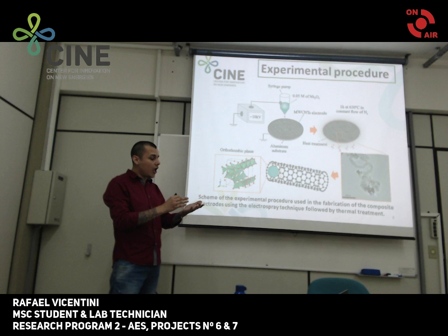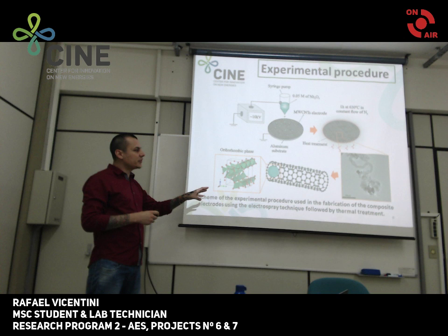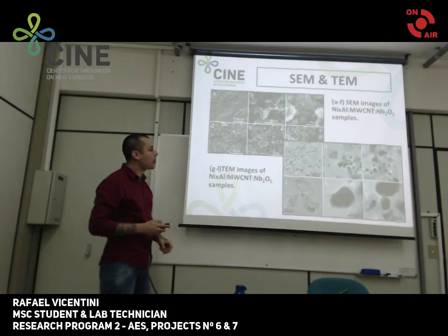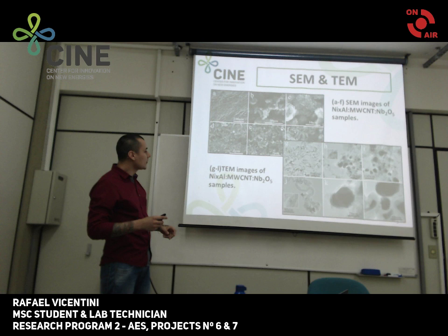In this presentation, I will just show you the main results, including cyclic voltammetry, charge and discharge, and electrochemical impedance spectroscopy. Okay, first of all, figures A to F show the scanning electron microscope images. Here, we can see the structure of this carbon nanotube decorated with niobium pentoxide. From figure G to L, we have the transmission electron microscope images. Especially in figures K and L, we can see a thin film of carbon covering the niobium pentoxide.